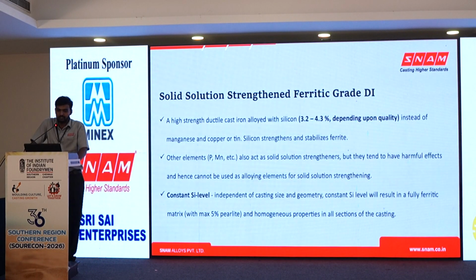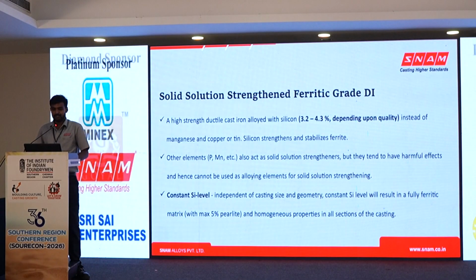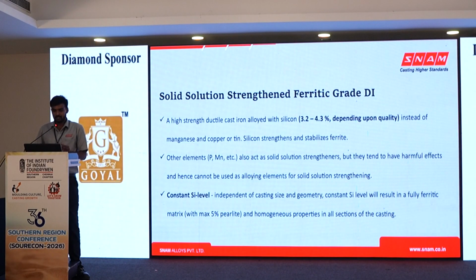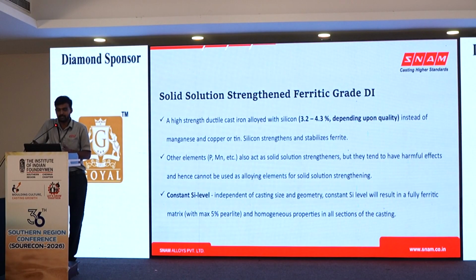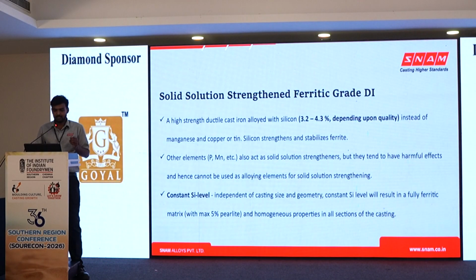So how do we produce solid solution strengthened ferritic grade ductile iron? Generally, to strengthen ductile iron, we use strengthening elements like silicon, phosphorus, manganese, copper, etc. But in producing ferritic grade ductile iron, we use silicon in the range of 3.2 to 4.3, depending upon the grade. Why silicon? Because silicon promotes the ferrite phase in a material. So it helps us increase the mechanical properties by increasing the silicon percentage.